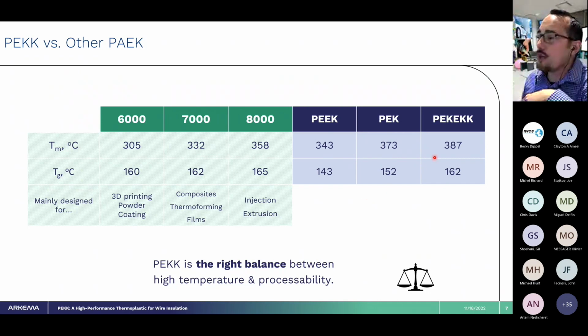What you'll see is that as you have more Ks, the melt temperature will go up and the glass transition temperature will go up. But in the case of PEKK, our material, you have the ability to tune that and retain a lower melt temperature while still keeping the higher TG. That's one of the big differences here for us.